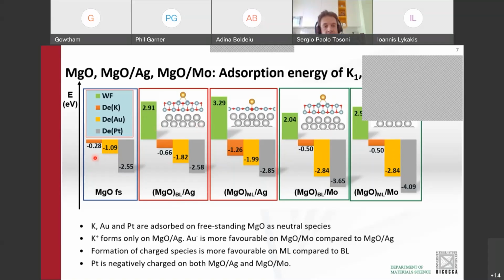And what happens is the following. If we start from potassium, we can see that potassium on freestanding MgO is only very weakly bound, like 0.3 eV. This is just a van der Waals dispersive interaction. But something happens as soon as we go to silver-supported MgO.